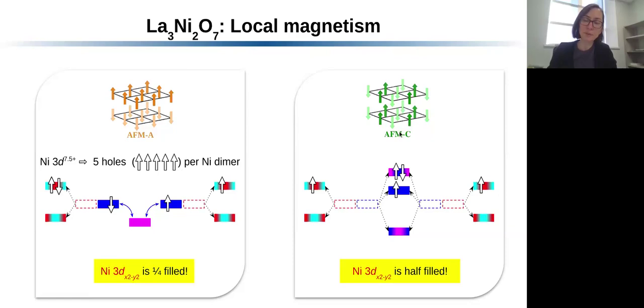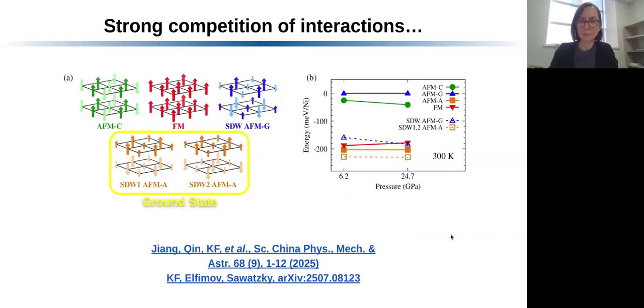But if you do the molecular orbitals properly, you look at this kind of splittings, and you can have a state where the occupations will be just right to produce the x squared minus y squared band, which would be exactly half filled. And that makes this system much more similar to the cuprates than what it looks like on the surface. This is just to show you that in my density functional theory, I can stabilize a state like that. And in this slide, again, I'm looking at different magnetic configurations.